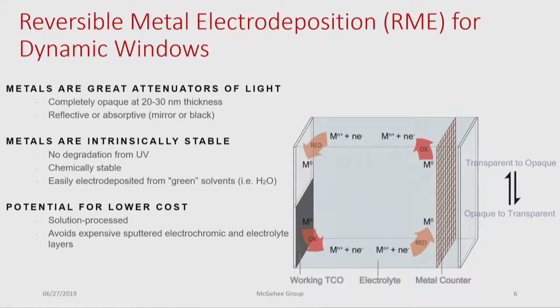So our dynamic windows operate by the reversible electrodeposition of metals. If you take a look at the diagram here at the right, essentially what we have is metal ions dissolved in some type of solvent. We commonly refer to this as the electrolyte. Now, if we apply a cathodic potential to some transparent electrode, commonly a transparent conducting oxide, or TCO, we're able to reduce these metal ions in the electrolyte onto the transparent surface, and this will induce optical tinting from a transparent to a dark state. By simply reversing the polarity of this system, we're able to reoxidize this metallic film back into the electrolyte, and it will thus return to its initial transparency.